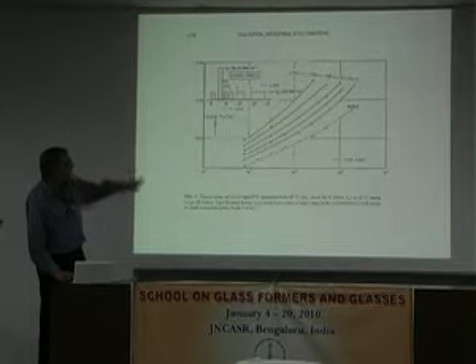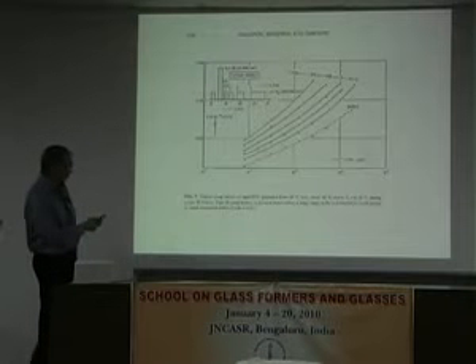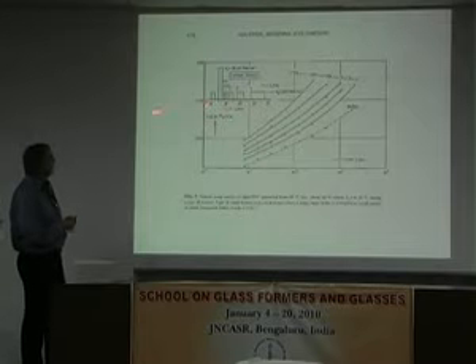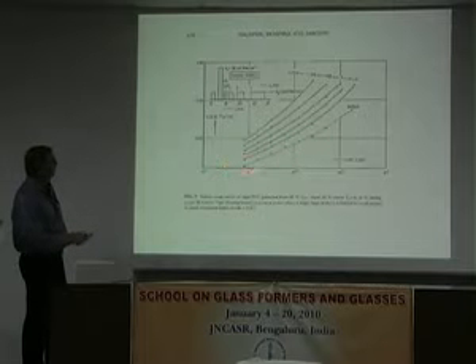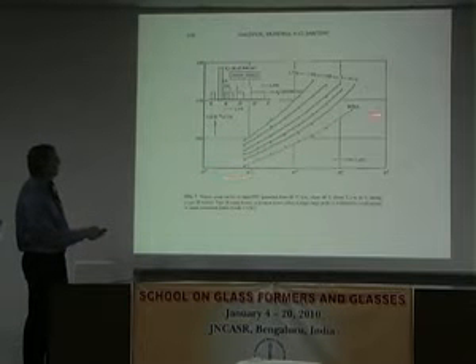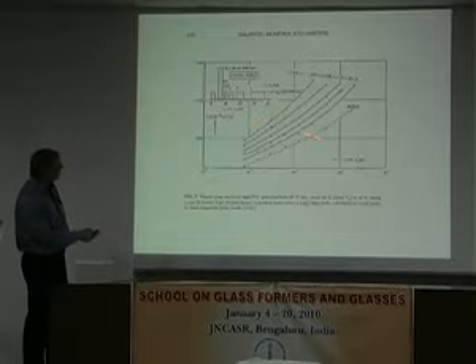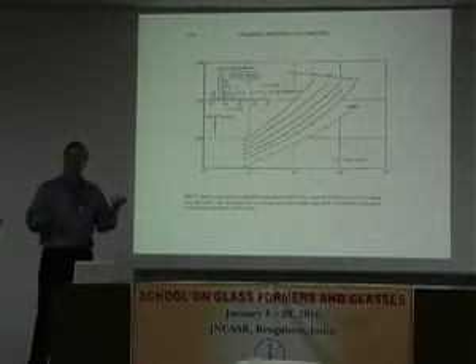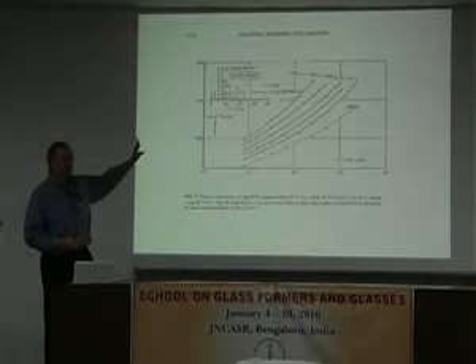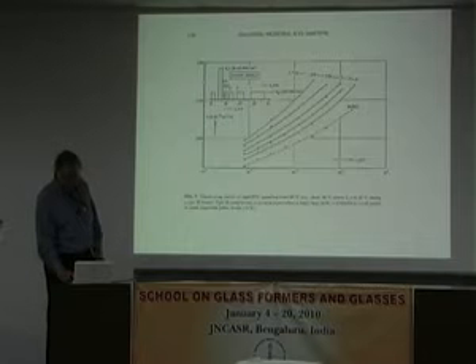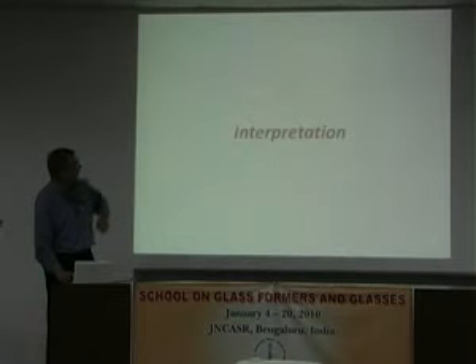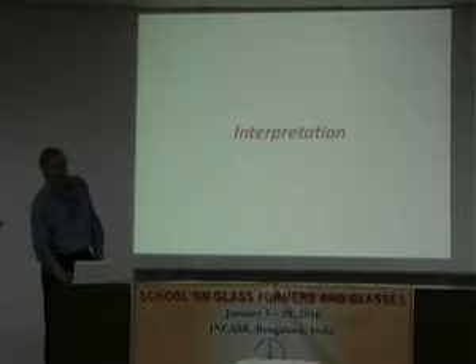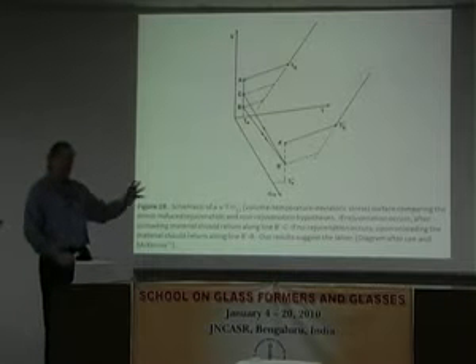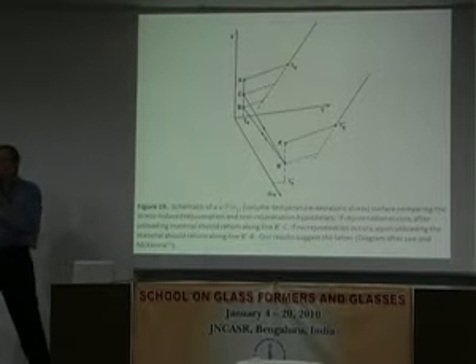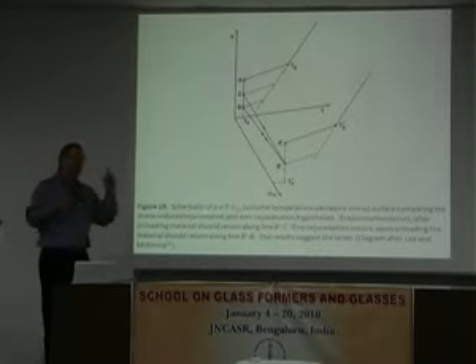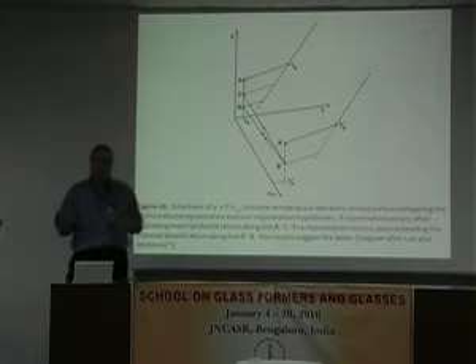Then there were some other experiments that Struik had done where he was aging the sample. This is the aging before he puts a big deformation on, and then he goes backwards, and he called that rejuvenation. This has the same problems as the other one, and we were able to quantitatively capture that, but I don't want to go over it. It's just too complicated. But ultimately, the question we need is some sort of interpretation about this nominal rejuvenation hypothesis.